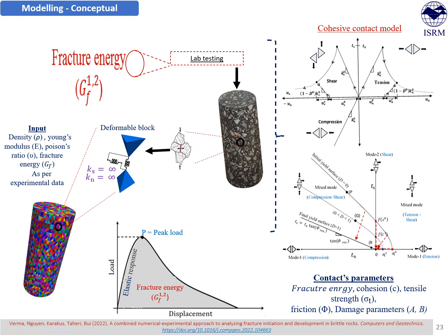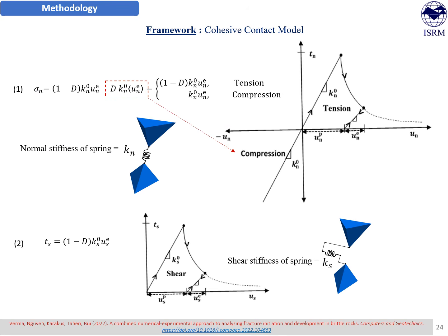intergranular interaction in a realistic manner, we need a reliable contact model, and at that time we realized that the available contact models in 3DEC Itasca were quite basic, and they were not quite accurate in terms of capturing the post-peak behavior in tension and shear and mixed mode loading conditions and so on. That motivated us to develop our own cohesive contact model and implement that in 3DEC Itasca. Now in terms of the cohesive contact model, the details can be seen in the publication as shown below in the slide.